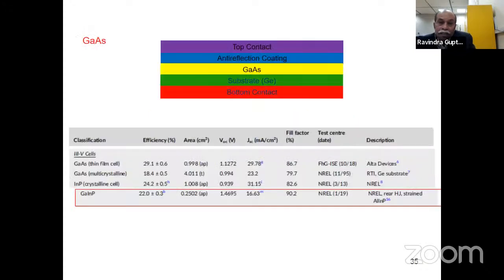Next is the III-V elements based solar cells. So here we have gallium arsenide, this is multicrystalline. We have indium phosphide, gallium indium phosphide. And if you see this thin film, thickness is in nanometer. It is 10 nanometer. Gallium arsenide thickness is very, very less, 10 nanometer. And it is on the substrate, germanium. Okay. And so the structure you can see is very, very good. But the problem is the arsenic. This is actually a toxic material.